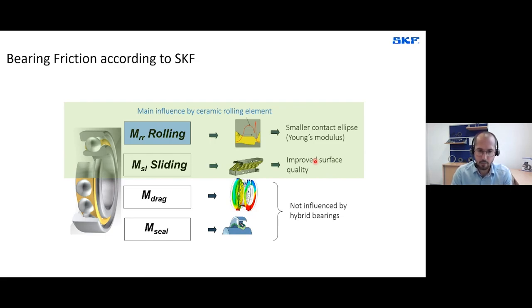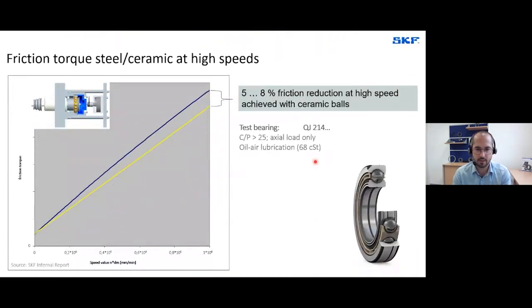And let's see how the pure effect of the ceramic rolling element is. So we have done internal tests, friction measurements on 4-point contact ball bearings, which are purely axial loaded and subjected to oil air lubrication. And what we have seen is that the friction torque is 5 to 8% lower than with steel bearings.